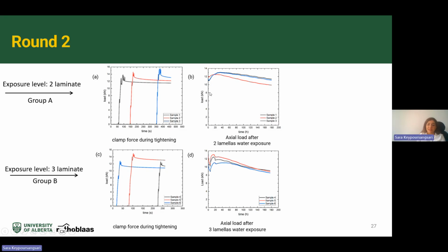The results show that this axial force, which is caused by the torque and moisture content change, starts increasing first until it reaches the peak. And after that, it decreases slightly. For group B, we exposed 3 layers to water, and we did the same thing, but in this stage, we stayed for about 5 hours to see the effect of the relaxation. And then we poured the water inside the bucket to increase the moisture, and you can see the results. Same as the previous one, this load increased until it reached the peak, and after that, it decreased. And here you can see in this figure that since we exposed more layers to the water, this decrease is more significant.